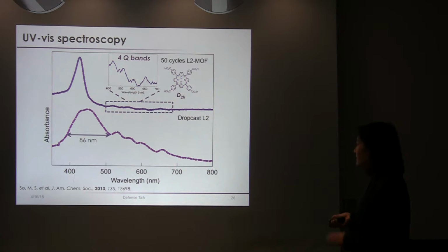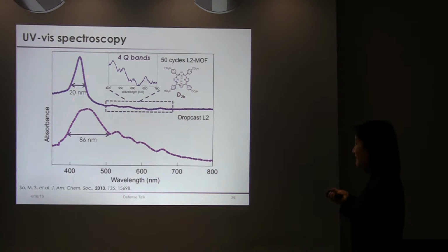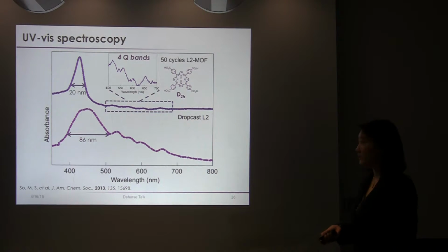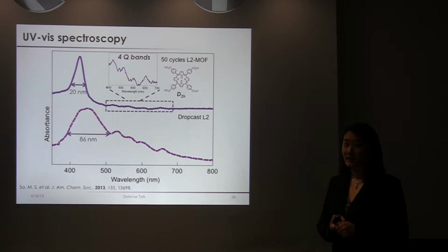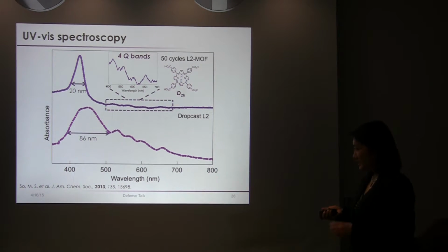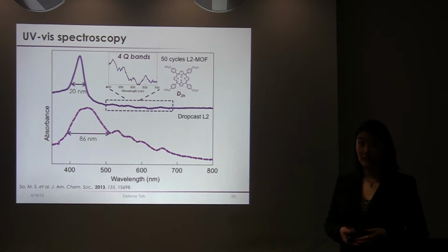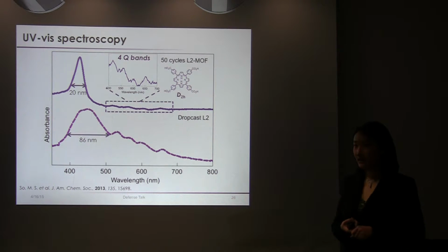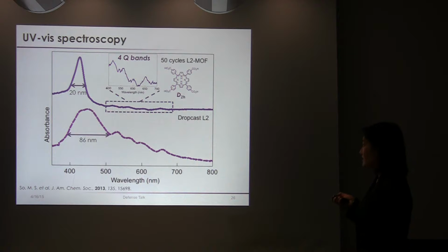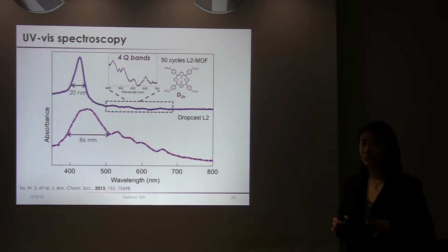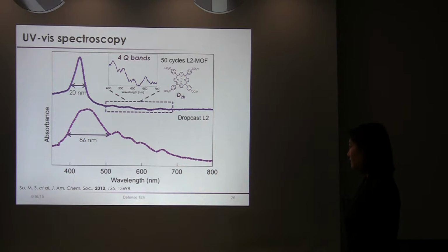Okay. And one thing that I also noticed was that the full width half max of just drop cast L2 porphyrin linkers was 4 times wider than that of the Soret band full width half max of an LBL assembled MOF film. So this tells us essentially two things. One being that in the drop cast form of just the L2 linkers, there's much more electronic interaction and aggregation. And secondly, in an LBL assembled film, you get very good chromophoric isolation. So this was a good demonstration of using LBL to form non-metallated porphyrin films.